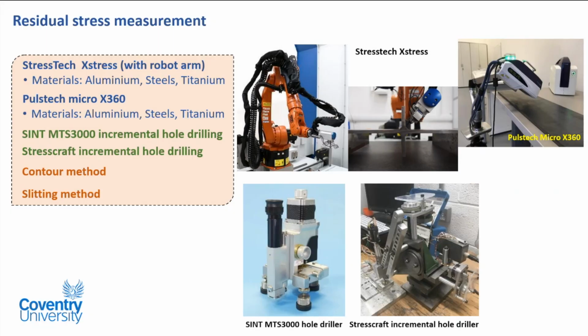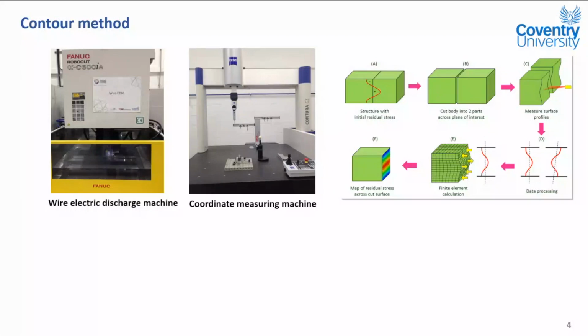And we also use a destructive method. I think we are probably doing quite well in the UK on the contour method. Basically on the left is the electrical discharge machine, and then the middle is a coordinate measurement machine. Then on the far right, the specimen contains residual stress. By doing a very controlled contour cut, the profiles being produced are really caused by residual stress release. So combined with finite element, residual stress can be measured.